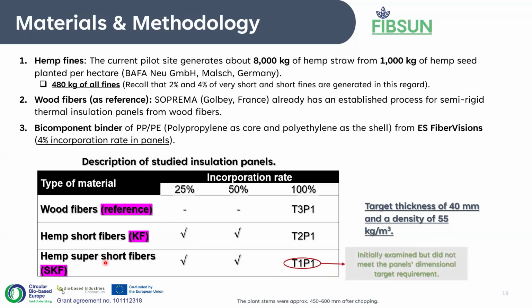But of course, we initially examined, this is also the goal. The goal was to examine all this incorporation rate. But what we noticed is that with the very, very short fibers, it was impossible for us to achieve the set goals of 40 millimeters with 55 kilogram per cubic meter. And I will tell you why later.